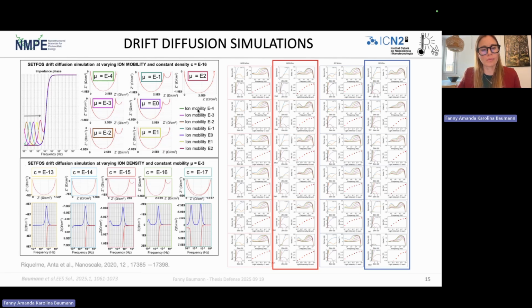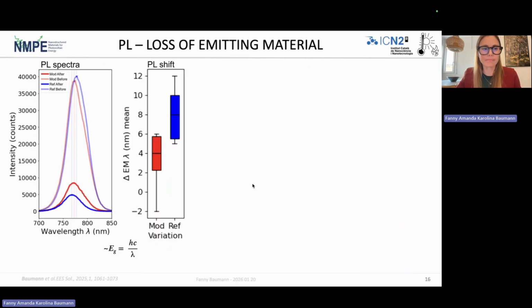And what we did was we adapted it to the architecture and the values we had from our solar cell, and we added some changes in ion mobility at a constant density versus change in the density at constant mobility. So we could clearly see that for the shape that we had, thanks to having every single data from our experiments automatically plotted, the tendency was more reproduced by using changes in ion mobility.